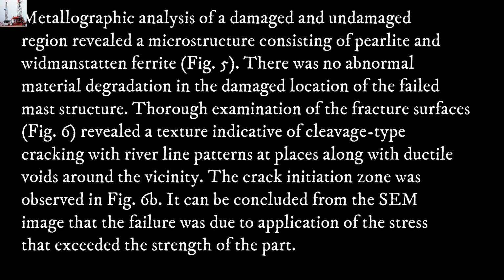A thorough examination of the fracture surfaces, Fig. 6, revealed a texture indicative of cleavage-type cracking with riverline patterns at places, along with ductile voids around the vicinity. The crack initiation zone was observed in Fig. 6b. It can be concluded from the SEM image that the failure was due to the application of stress that exceeded the strength of the part.